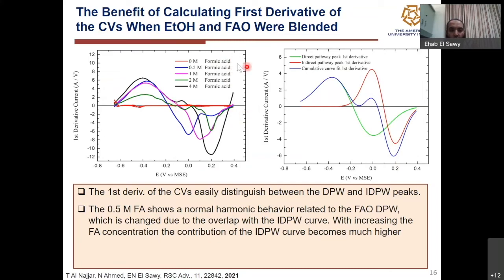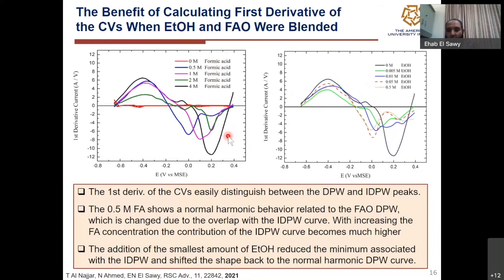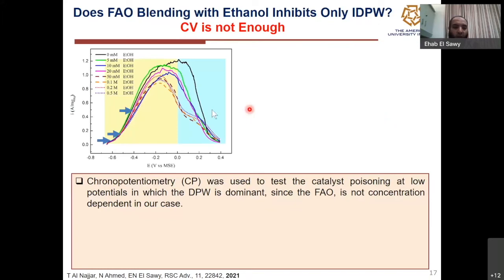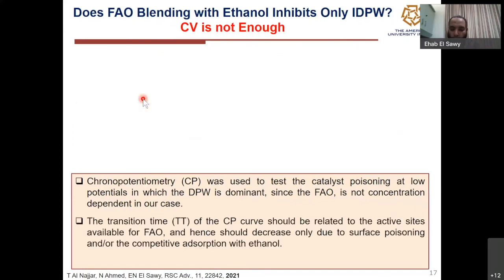With increasing concentration of formic acid, we shifted from the normal harmonic shape to another peak that is related to the indirect pathway. Once we added the ethanol, this peak related to the indirect pathway is suppressed. At this stage, we would just say, hey, we suppressed the indirect pathway, this is a good blend, and it's perfect. However, that's not the case. The CV is not enough to say that the direct pathway is safe and only the indirect pathway is suppressed. So we took chronopotentiometry at the small currents in the direct pathway and tried to test that using chronopotentiometry.